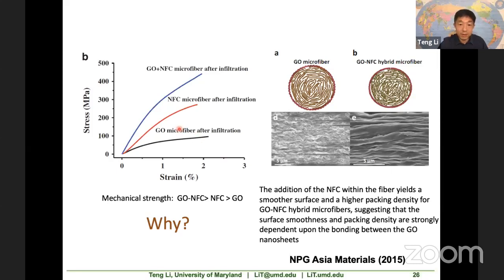We make the fiber purely using graphene oxide. Here, this is the dark curve. This is just pure graphene oxide fiber. We also make a fiber made of pure nanocellulose, which is the red curve, okay? If you call this curve A, material A, which is pure graphene oxide, and pure NFC is material B. Now, typically if you mix A and B, you get something in between, right? So not better than both.